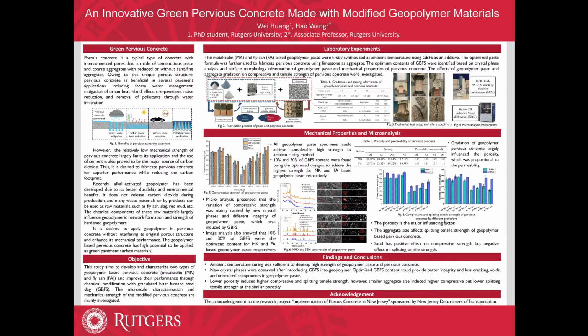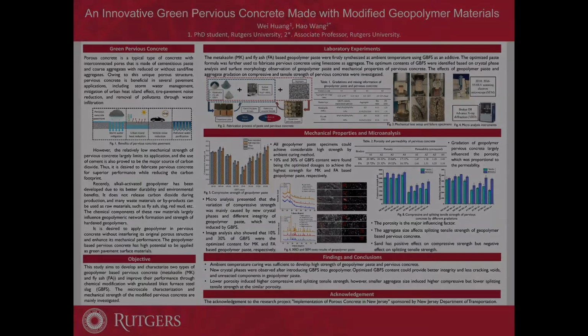We also found the lower porosity induced higher compressive and splitting tensile strengths. However, smaller aggregate size induced higher compressive but lower splitting tensile strengths at the same porosity. That's all. Thanks for listening.